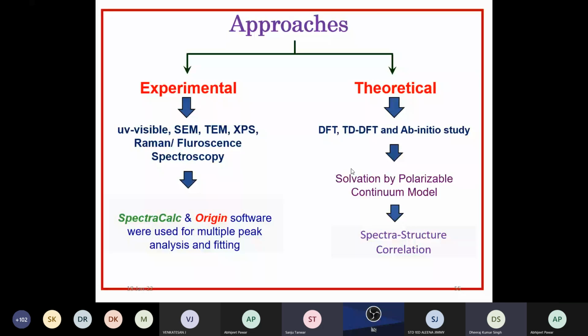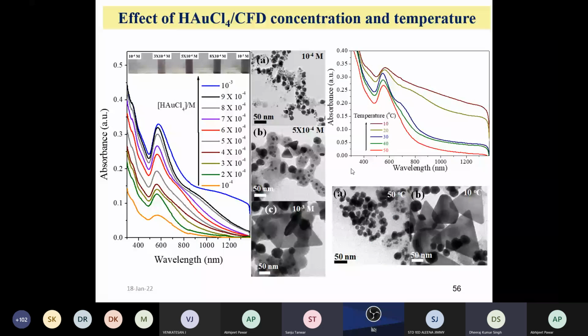After synthesis of gold nanoparticles directly using antibiotic, the first step was UV-visible absorption spectroscopy. This diagram shows the spectra, with wavelength on the x-axis and absorption on the y-axis. We started from 10^-4 molar concentration, going from bottom to top, and the blue one is 10^-3 molar concentration. After synthesis, you can see a sharp peak at 550 or 580 nanometers. If the peak comes at 580 nanometers, it ensures successful synthesis of almost polydisperse spherical nanomaterial.